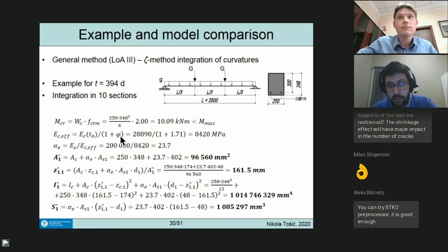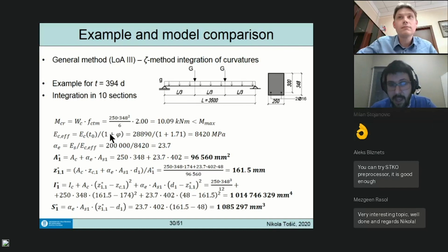I'm going to use the measured creep coefficient, which is just the creep strain divided by the initial strain. That's why I'm going to use it with the modulus at the time of loading, and not do that separation into the modulus at 28 days and modulus at loading, because I'm not calculating the creep coefficient.